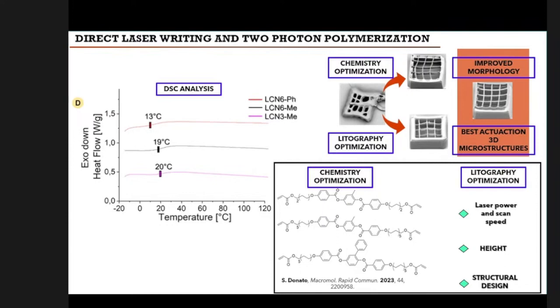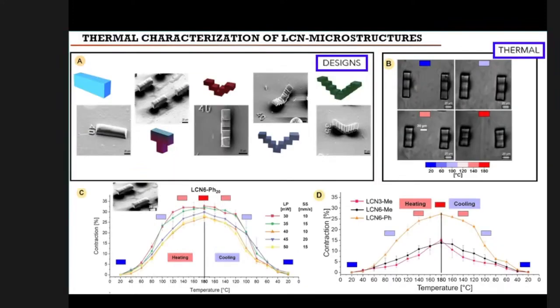But not only that, because I also have to use a lithography optimization, changing the printing parameters, in this case laser power and scan speed, but not only, because I changed the height of the structures and also the structural design. As you can see from the first image, I started to produce micro blocks completely stuck on the glass. Then I moved to suspended structures, so a suspended block. And then I increased the complexity of the system, producing stages with different steps. All these microstructures are thermally characterized under cycles of heating and cooling in order to demonstrate the contraction of the microstructures obtained and the reversibility of the process.